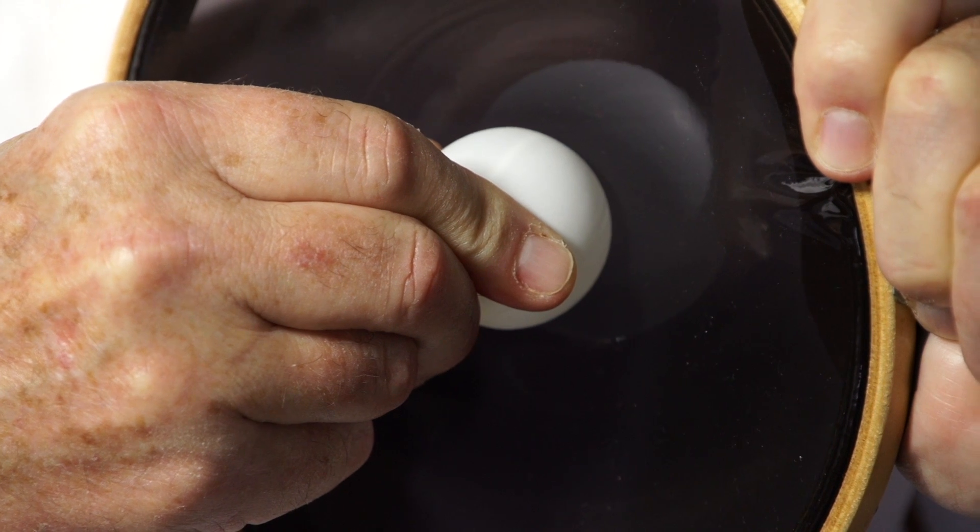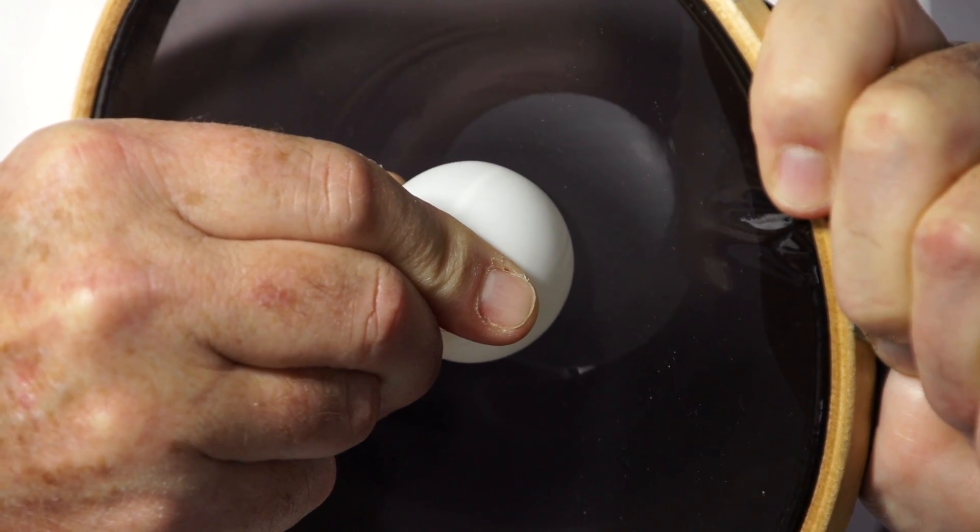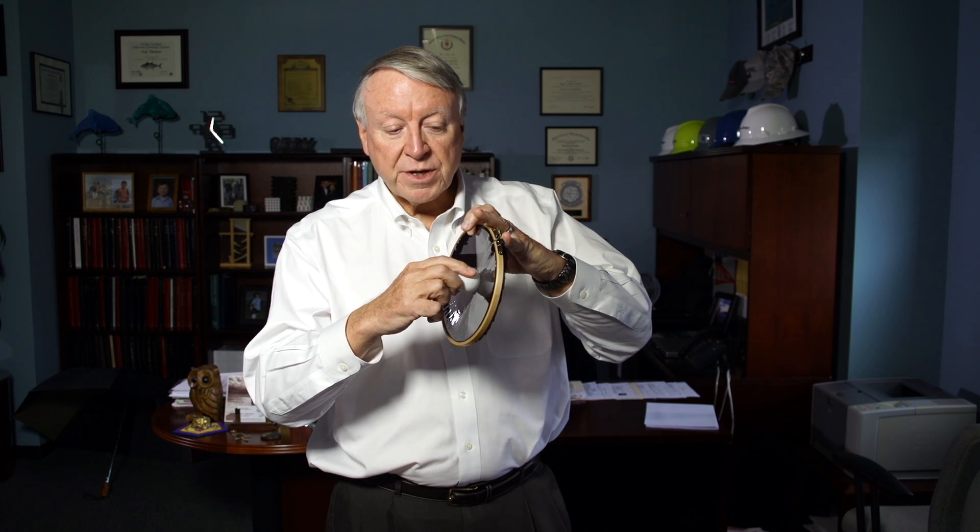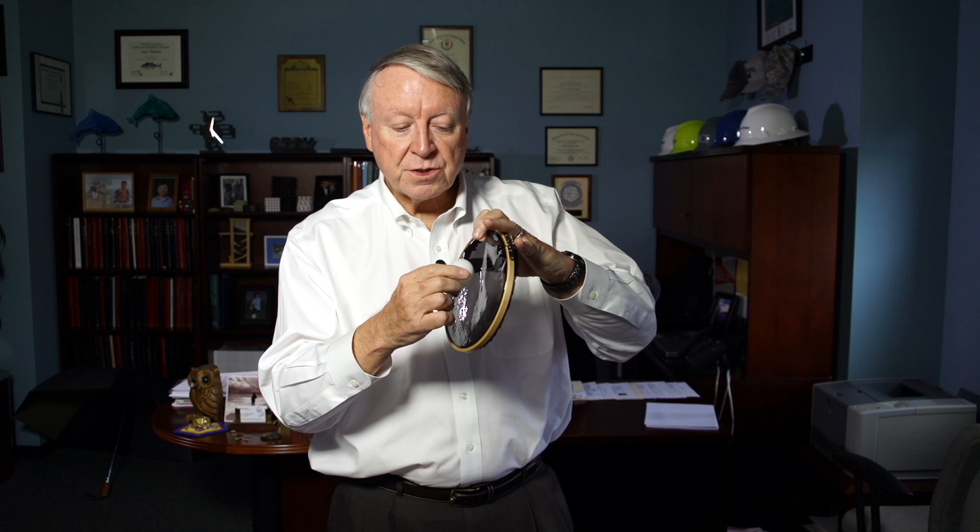Because graphene is very strong, very stiff, and very low density, this cone spreads out to quite a distance in the material. The kinetic energy of the sphere is transferred to the membrane before it pushes through and eventually exits on the other side.